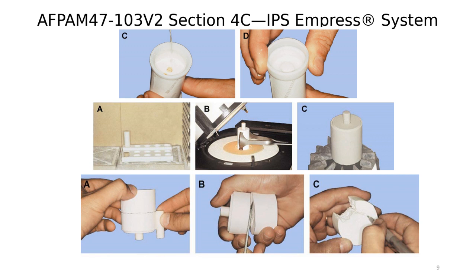Once the program finishes, the oven stops by itself. Remove the ring and let it bench cool. Under no circumstances should the ring be force-cooled by applying air, water, or placing it in a cold area, because the material inside is still hot and is a glass-like material. Exposing the ring to cold temperatures may cause the copings or restorations inside to break or fracture.